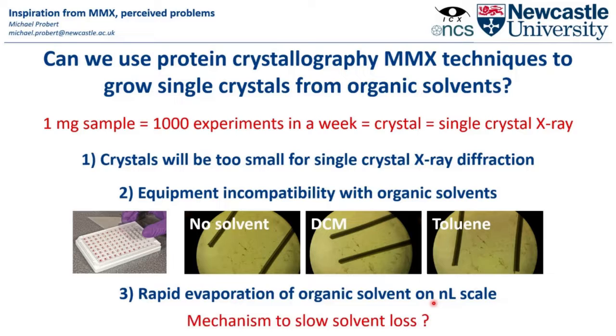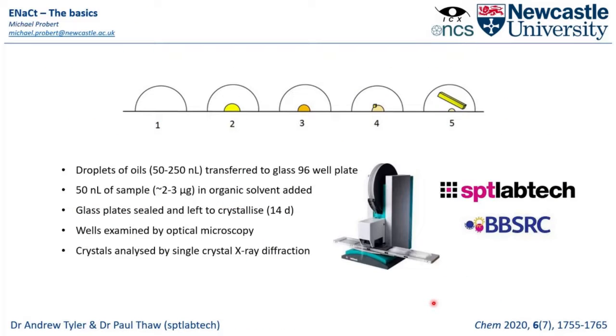So can we think of a mechanism to slow the solvent loss? And this was our challenge. Obviously the fact that I'm talking to you shows that we managed to succeed. But how did we do that? Well, we had this idea that we ended up calling Enact, so encapsulated nanodroplet crystallization, where we would take a dispensing robot, dispense an oil droplet, an inert oil, and then inject into that droplet our analyte inside a solvent. So this cartoon across the top is really showing what we hoped would happen.